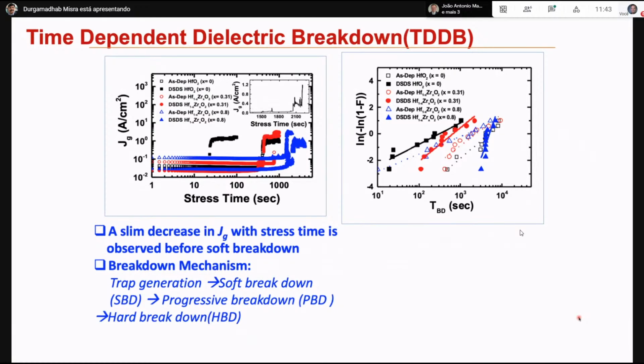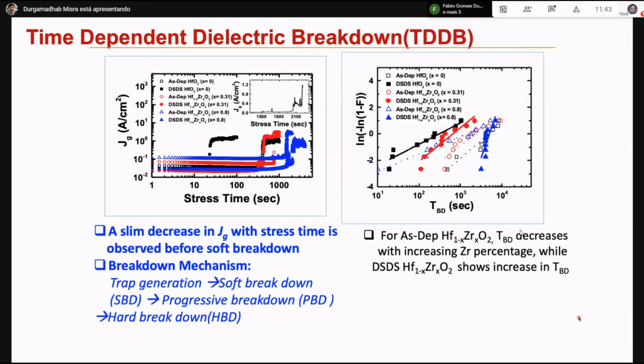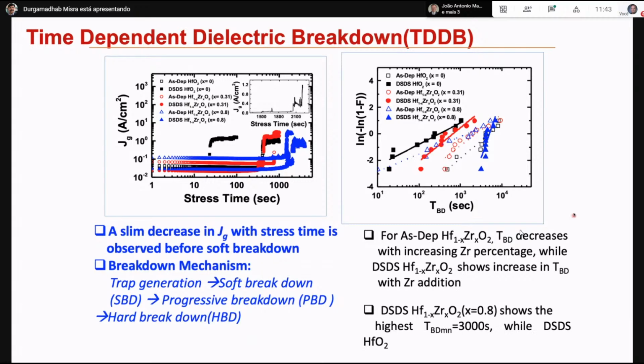And the leakage current, and as I mentioned, the time-dependent dielectric breakdown. We saw that when the leakage current is lower, the time to breakdown is also quite high. In this case, for the DSDS sample with 80%, we have a very large time to breakdown, because we estimated a 10-year breakdown. This also shows the charge to breakdown from the Weibull plot, and the leakage current, compared to the other devices. Even the DSDS hafnium oxide was not that good. So this gives some idea of how this is happening.